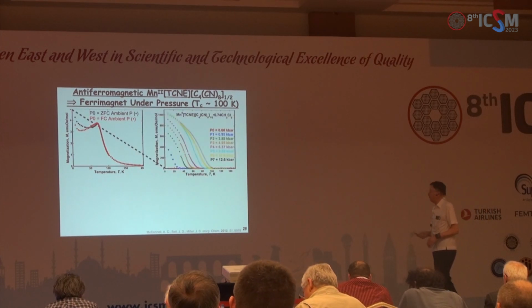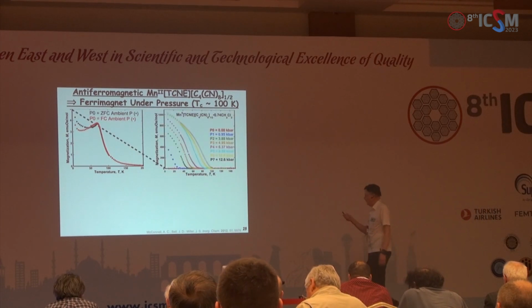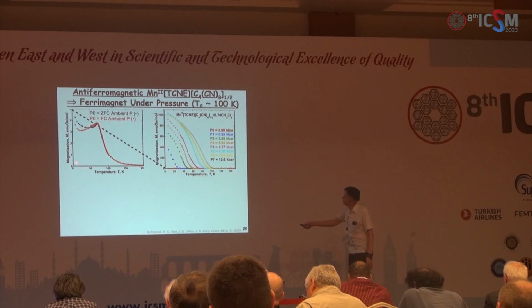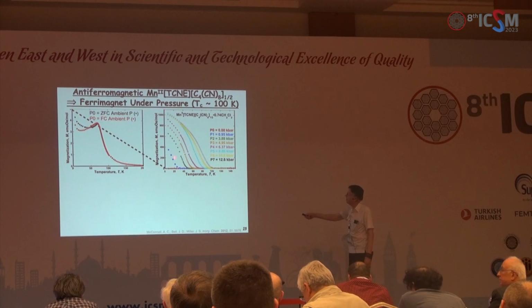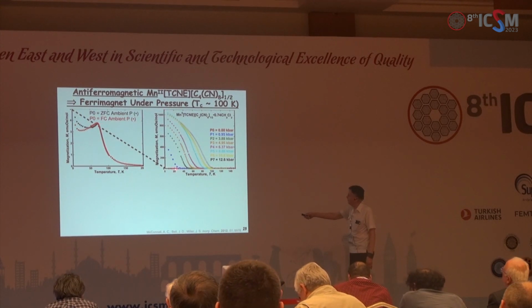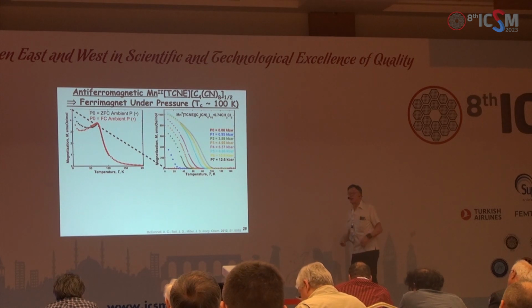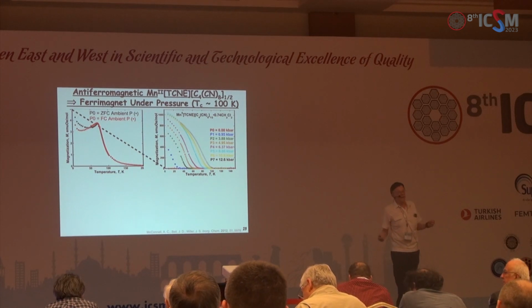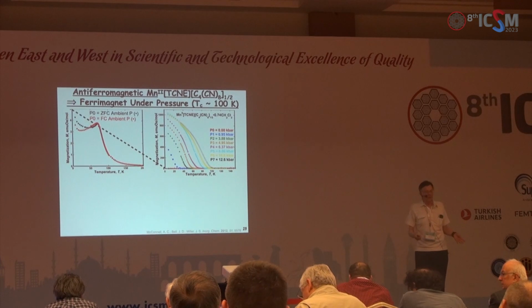When I put pressure on it, this data point—because this axis goes from 0 to about 8, and this one goes from 0 to 1100—so that red point is over here. And as we put pressure on it, we actually can get growth in ferrimagnetic behavior at higher pressure.